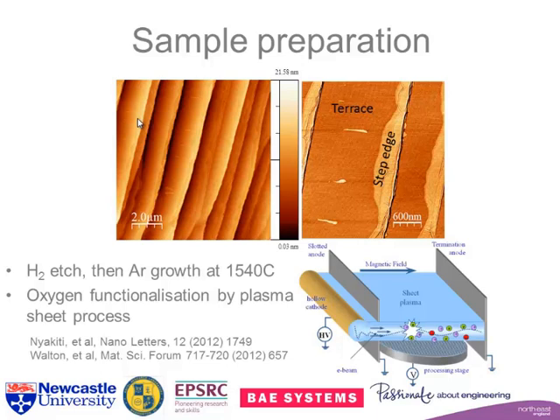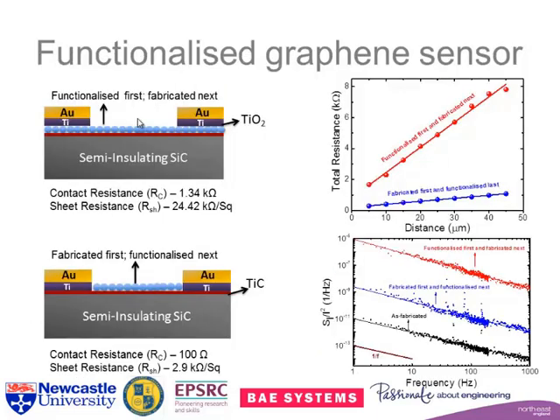The oxygen functionalization process is shown here. So it's a sheet plasma, which gives us a very low incident energy of the oxygen. Because graphene is all surface, it's very, very easy to damage the surface. And one of the critical steps of the work that we're reporting actually is in the development of the process to enable this. So there are two possibilities.